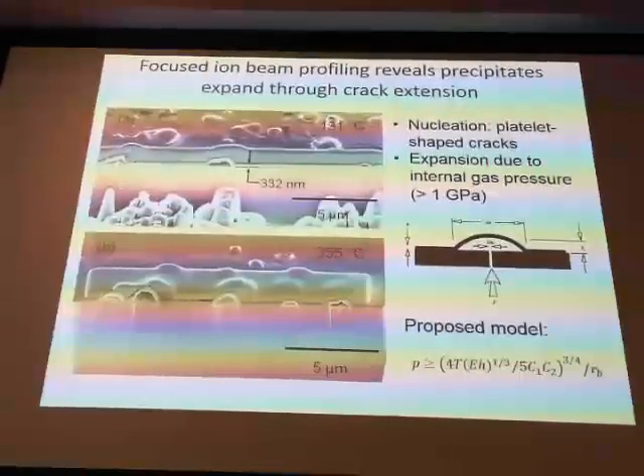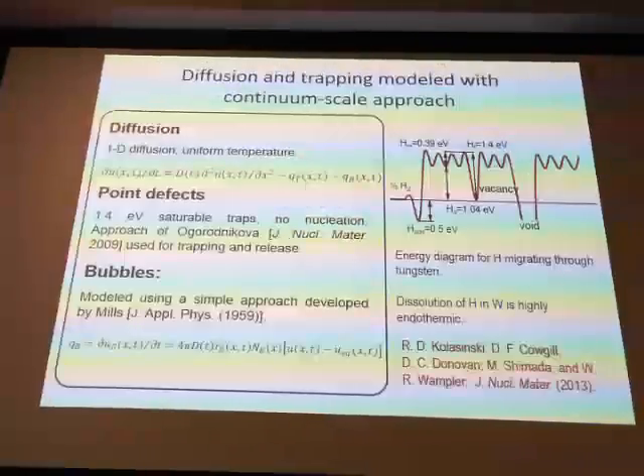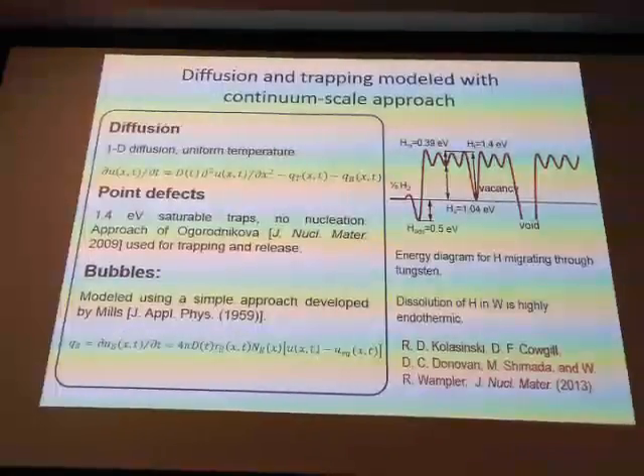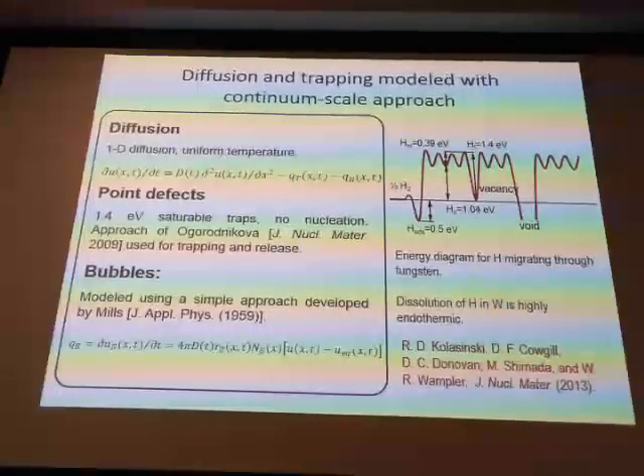And so we did some focused ion beam profiling, and you can see the shape of these defects. There basically looks like a little crack formed near the surface, and then it filled up with high pressure gas, and essentially inflated this near surface region here. And so we tried to develop a model that could describe this in some detail.